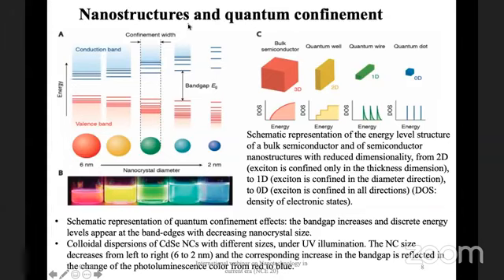So if you do a simple Schrödinger wave equation solution of a quantum well, where you just change the width of the quantum well, you will see that if you decrease the width of the quantum well, the energy states will be pushed up and the gap will increase. And that's the quantum confinement effect. And the width is defined by the diameter of this quantum dot, which is a spherical cadmium selenide nanoparticle. So we can design a whole range of these nanoparticles.